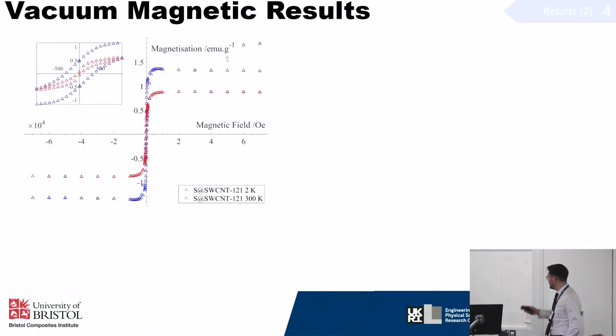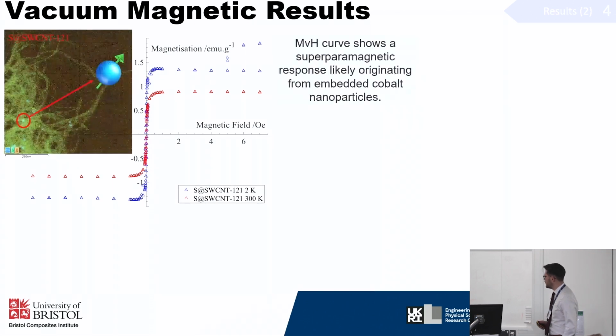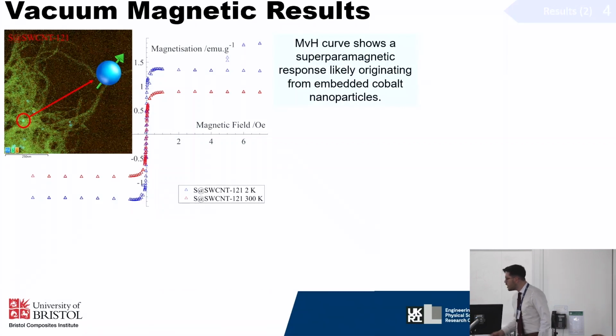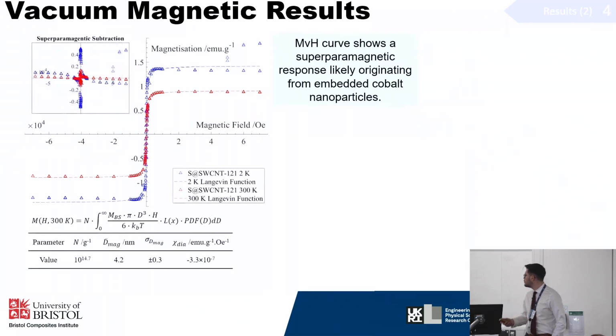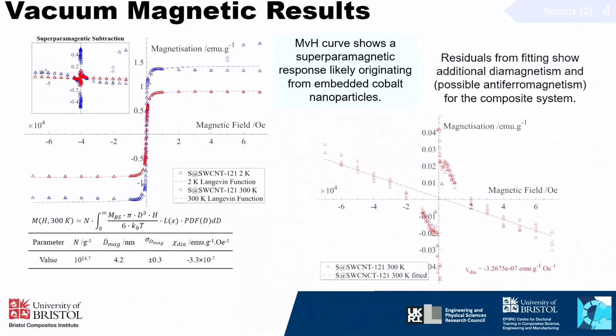As for the magnetic results of these materials, we can actually see that there's a ferromagnetic, superparamagnetic response in this material, shown by that sigmoidal curve at high temperatures. This is something that's characteristic of ferromagnetic materials. So we can see here isolated pockets of cobalt within our sample. This isn't too bad, even though it's an impurity. Now we know it's there, we can model it, and we can subtract away that superposition and be left with what is just our carbon and sulfur and see a diamagnetic response inside this.